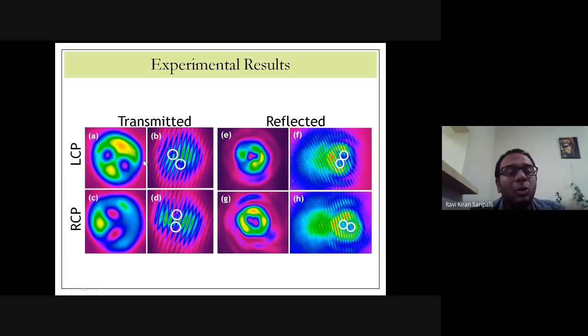The splitting of the vortex into two single charges can happen when a vortex beam is transmitted through a turbulent medium, and that is what we observe here. And when you do the interference, you can see these fork structures. So this is a topological charge 2, or an OAM of order 2, which is produced. And when you switch the input polarization from left circular polarized to right circular polarized, you see that these forks flip. That means that the OAM becomes +2 to -2, just to conserve the total angular momentum.